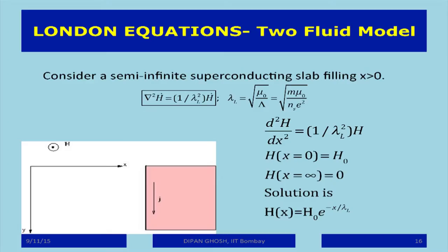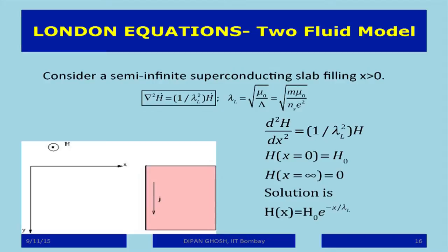And I've told you several times this 1 over e keeps on coming, because that always is a measure of how far a field penetrates. Okay? This happens whether you are calculating the skin depth in a metal or whatever. So therefore, according to London, there is a distance lambda after which the magnetic field or magnetic flux is effectively screened. Magnetic flux is effectively screened. So this depth to which the magnetic field penetrates inside the sample is what is known as the London penetration depth. And mind you, I can actually calculate this because everything there is known to me.